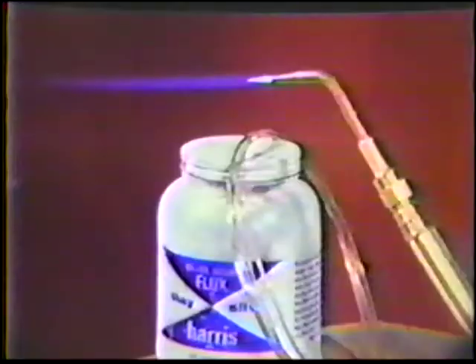The workpiece for this practice is made of 2 pieces of copper, overlapped to form a lap joint. The clearance between the pieces should be 1 to 3/1000ths of an inch for proper capillary action of the liquid filler metal. In this case, simply laying one small flat piece upon the other will provide about the right space. A 2x carburizing flame will be used for this exercise.